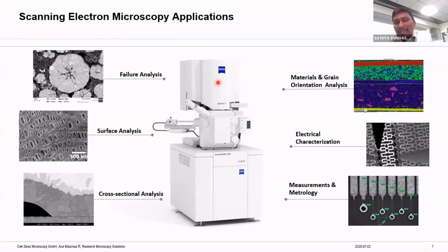The capabilities, whatever we talk about, all come because of the column strength, the design of the column, which Zeiss has as its unique nature. In that unique design, it can allow very hard samples, samples which can sustain 30 kV, and even you can image those samples which cannot take an accelerating voltage, around 100 volts or 200 volts. Even lesser than that, we call it ultra low imaging. You can perform the analysis at 100 volts and get high resolution. So these are a few areas of application for electron microscopy.